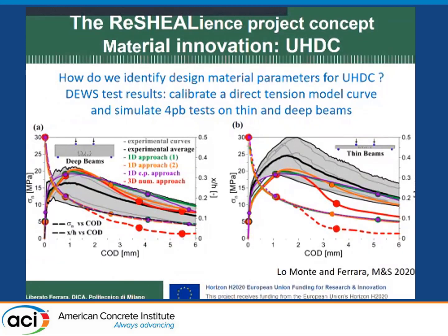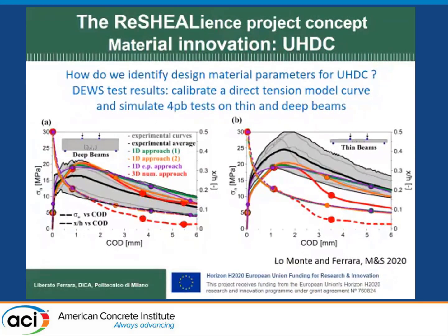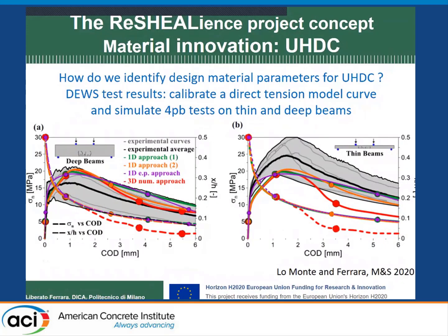And you can see the orange, purple, and green curves which replicate either the upper bound or the lower bound of the response. And there is also an elaboration on how the neutral axis depth evolves in these specimens along the test.